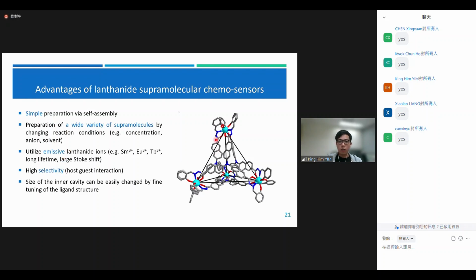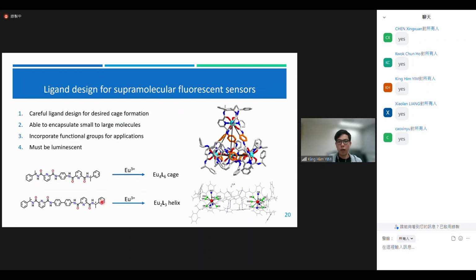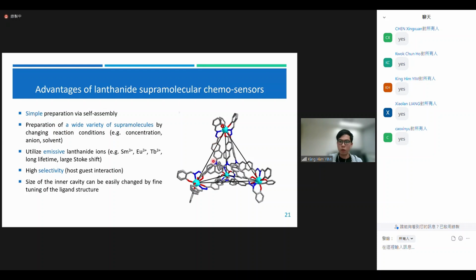And also, this kind of cage exhibits very high selectivity towards the analyte because of host-guest interaction. If you have a very, very large analyte, then it probably cannot go inside the cage. And the size of the inner cavity can be easily changed by fine-tuning the ligand structure. Most of the time this applies, but in the previous example that I mentioned, this does not apply. But there are many reports that a slight increase in the linker size can still form the same product, and the cavity can be simply changed by increasing the number of phenyl rings on the linker.